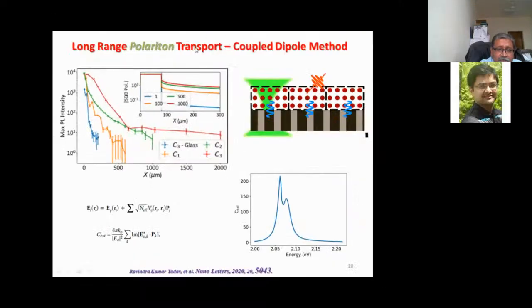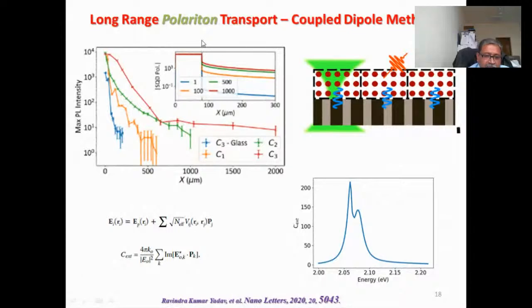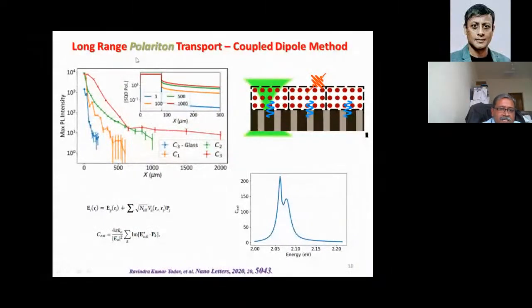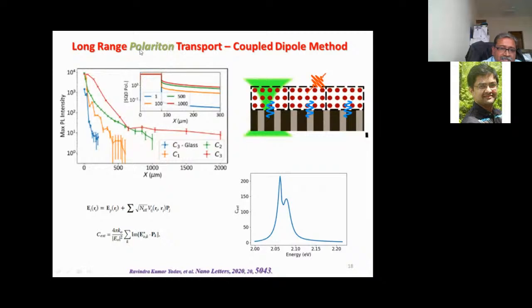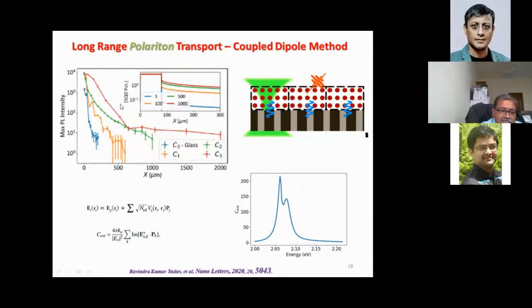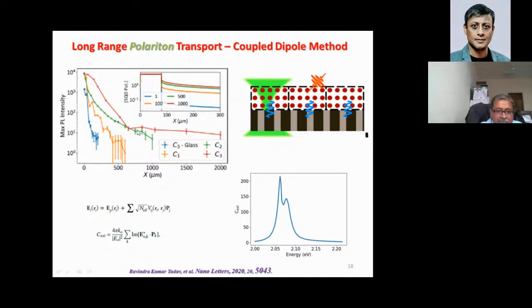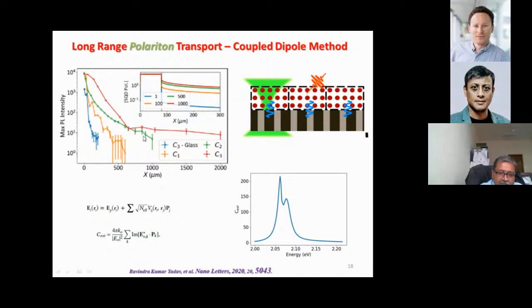So this is quite fascinating because it's suggesting that, as we know, light of course can travel over long distances, but the excitons which are carried by the quantum emitters cannot. They have very short range diffusion, that is well known, hundreds of nanometers maybe. But here, when you combine, you create these hybrid states, then they can, in some sense, retain the ability of, for example, the photons to travel long distance. Now you have a hybrid mode, which you are able to transfer information over very large distances.